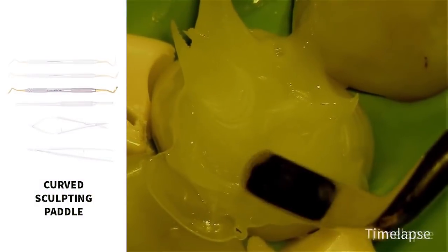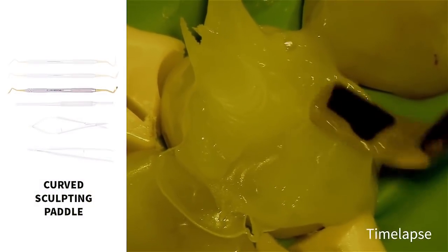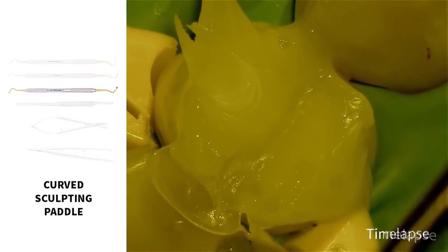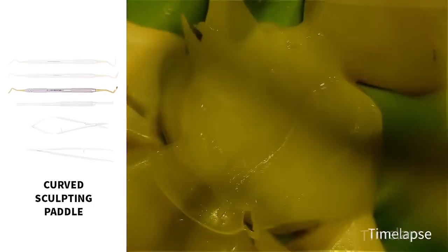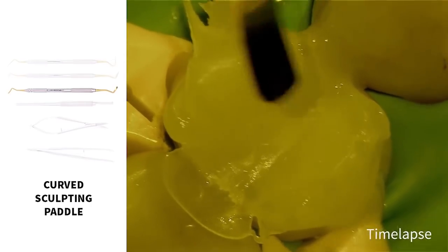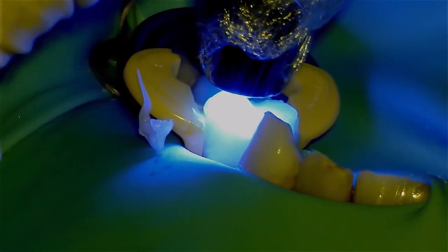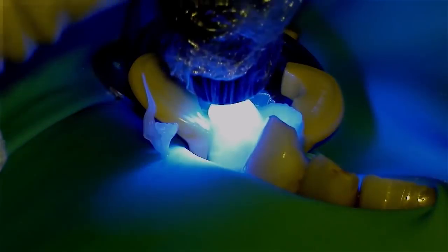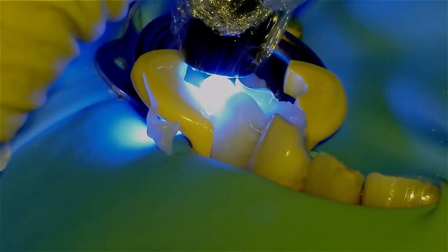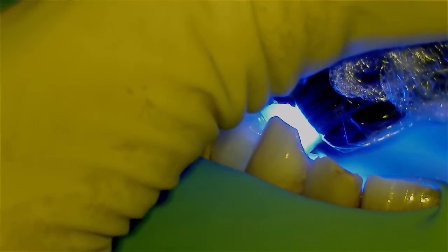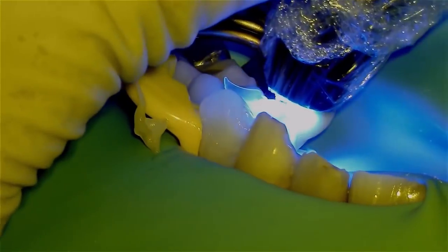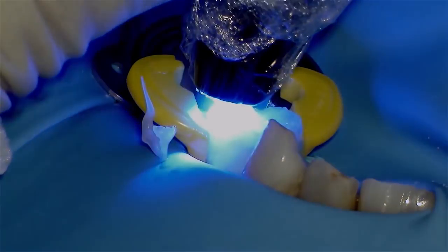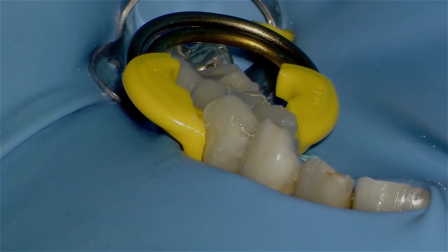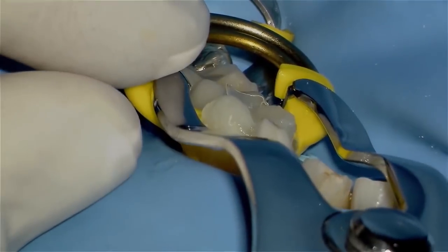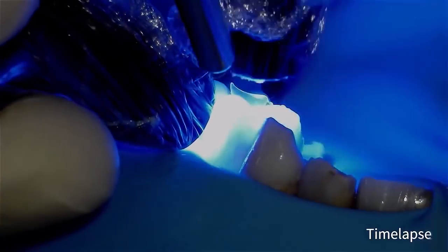And you need to inject feeling back pressure, taking advantage of the thixotropic nature of composites, feeling the back pressure, sort of riding this hovercraft of back pressure. And then once you see the flowable composite has been pushed out the path of least resistance buccolingually, we'll create some gentle anatomy, a central groove that helps for light curing and also to mitigate some cross-tooth polymerization shrinkage stress. Try saying that 10 times quickly. And then we'll go ahead and do a quick light cure.